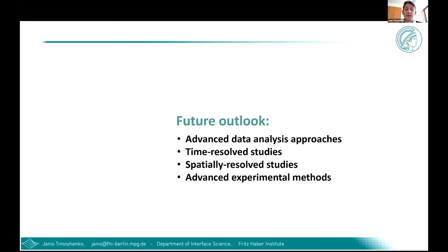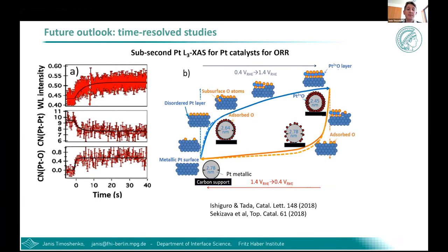Furthermore, the abilities of XAS during the last years have been extended by advances in instrumentation. For example, it was recently demonstrated that time-resolved XAS studies are now possible in an electrochemical environment with sub-second time resolution. In this proof-of-principle work, it was demonstrated that both XANES features and geometrical structure descriptors such as metal-metal and metal-oxygen coordination numbers can be tracked with excellent time resolution. And more importantly, different characteristic time scales observed for the evolution of these different features in our XAS spectra can now be linked to distinct steps in the quite complex overall picture of processes which take place on the surface of the catalyst during its exposure to potential and the electrolyte.